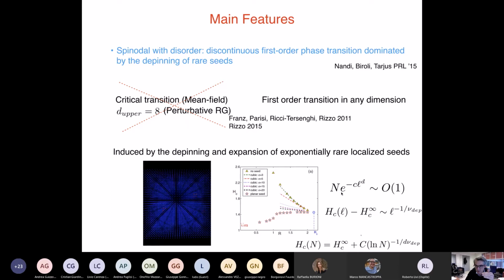And this means that, putting the two together, the critical value for a given system size will go down with n in a logarithmic way, which is log n, because it's due to this very rare effect. And so this is extremely hard to see if you don't put the seed by hand, and if you put the seed by hand, of course, instead you can see it.